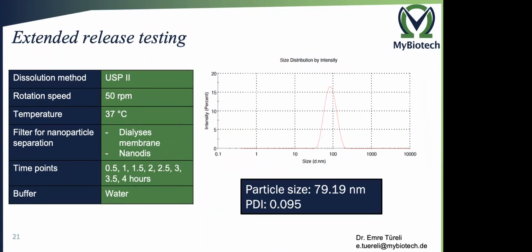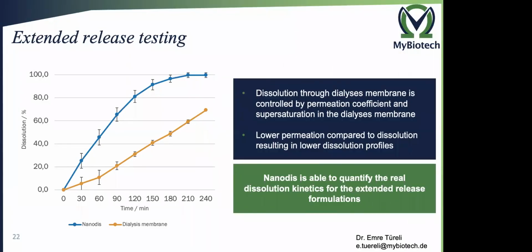On the left side, again, our dissolution method: we have used the USP II, 50 rotations per minute, 37 degrees. Either we put the formulation in the dialysis membrane and then put it into the vessel, or we introduce the formulation directly into the vessel and use the Nanodis filtration. We have done the dissolution for 4 hours in water. On the right side, these are the particles that we use for this dissolution study, with around 80 nanometers particle size. So when we look at the results, what we see is the orange one is the dialysis membrane, which means in the dialysis membrane you have different processes.